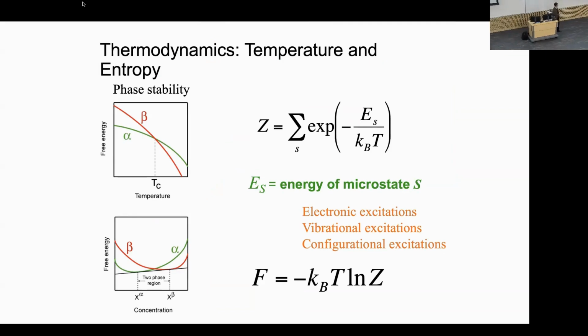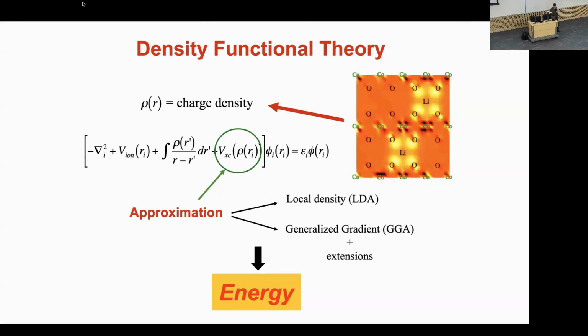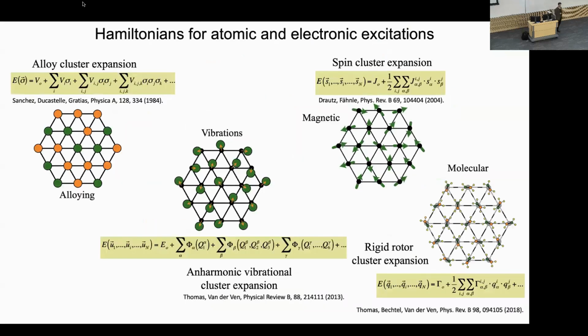So to overcome this challenge of calculating these kinds of thermodynamic properties, starting from a first principles method, we need a way to interpolate and extrapolate these expensive calculations. And the way we do that is with essentially surrogate modeling. Nowadays, people call this machine learning or surrogate models. But really, this is essentially coming up with functional forms to interpolate expensive density functional theory calculations. And they're called surrogate models, or we can call them effective Hamiltonians, or generalized cluster expansions.